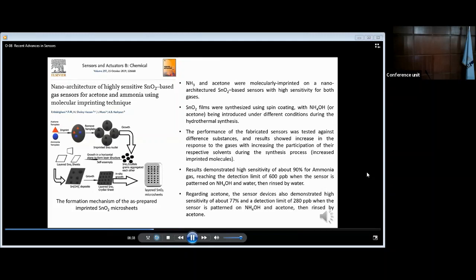This sensor showed very good performance. As a result, it demonstrated high sensitivity of about 90% for ammonia, and the detection limit was as low as 600 parts per billion. While for acetone, the sensor device demonstrated high sensitivity of about 77% with a detection limit of 280 parts per billion.